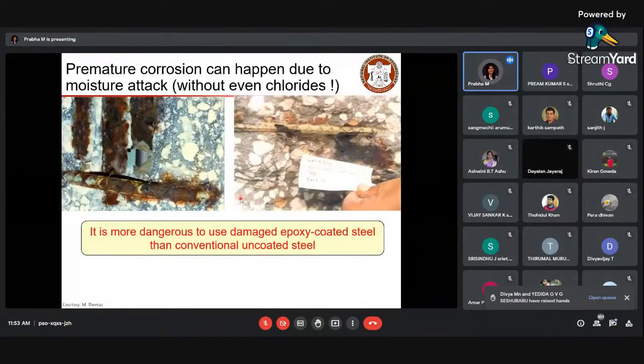You can see the premature corrosion observed in such cases due to moisture attack without even chlorides. There is no coating at all left; the coating has come out, and you can see how severe the corrosion is at this place. So it is more dangerous to use damaged epoxy coated steel than conventional uncoated steel.